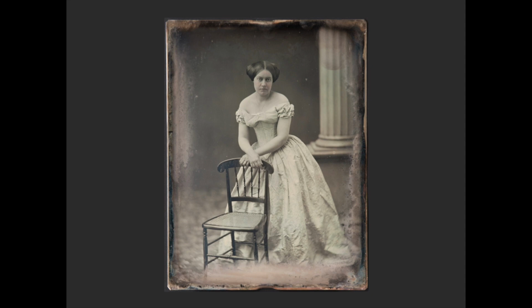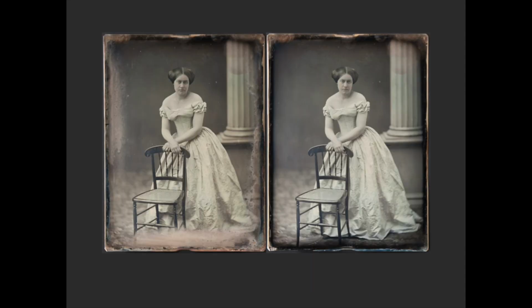So I developed a system, practicing on my own plates, to see what would be effective, and with a local treatment of ammonia solution, was able to dissolve the silver chloride. So this is the plate pre and post treatment. The ammonia will not remove sulfur. I had no intention to remove the sulfur on the plate. I wanted to remove the disfiguring white haze.